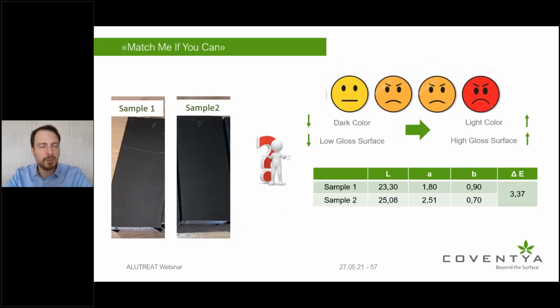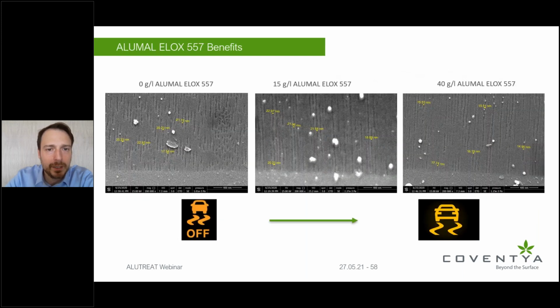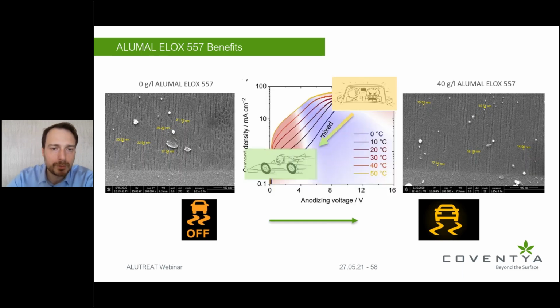And again, returning to our example with the black, the more alloying elements you have, the more changes in the production cycle you have, and even with anodizing, where the black is supposed to be the easiest color, you're going to have problems. So this was our part of the webinar about the 557. So in order to control the growth and the distribution of these oxide layers, it is paramount to control the anodic oxidation cycle. Therefore, you need to control not only the voltage or the amperage, but quite frankly, the speed at which the anodic oxide is growing.